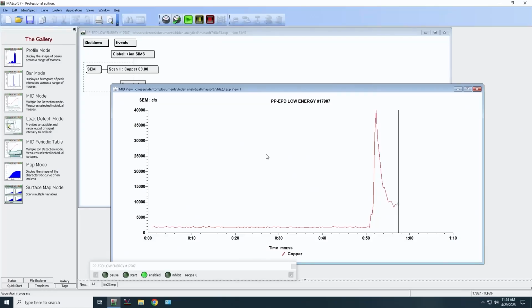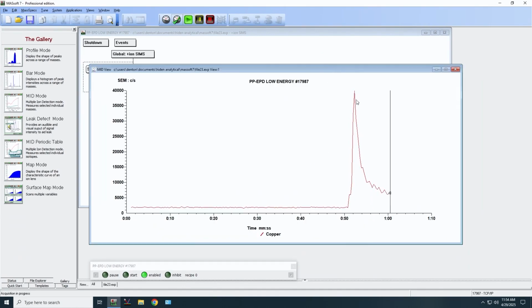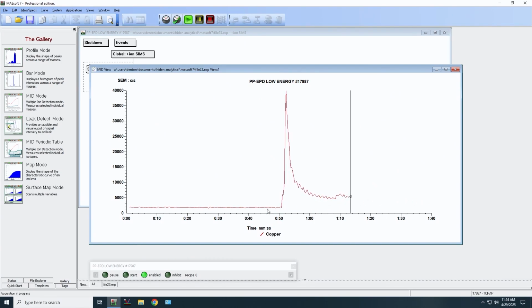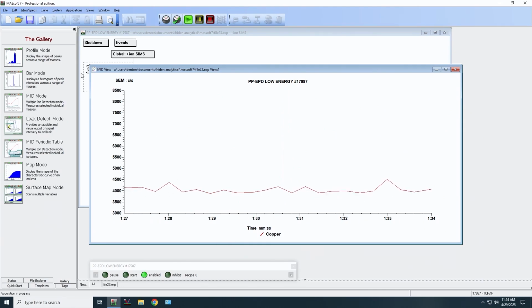So now if we go back to the SIMS data, every time you open the shutter, there's always this initial spike. The top layer on this sample is actually silicon, so we're still not seeing copper. You'll see the quote-unquote background level actually goes up and down under a lot of conditions. It's dependent on vacuum level, and on basically how many ions of any type are entering the SIMS head. With our etch active, we're getting a little bit more ions into the SIMS head, even though they're not copper, and the background level is now approximately 4,200 counts.